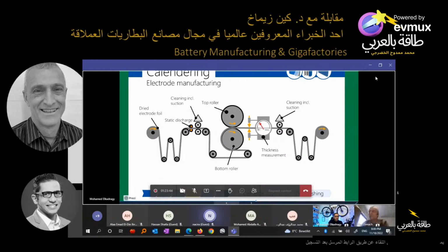Now you could say, oh, well, let's put more energy in my electrode. Let's crush it even more. Well, then your pores become too small and you can't get your lithium ions in and out. So there's a balance there. If you crush it less, lithium ions go in and out faster. It's faster charge and discharge, but you fit less total energy in your cell. If you crush it more, now you can pack more electrode in your cell, but your charge and discharge rate, how fast you can charge, how much power you can get out, goes down. So there's a trade-off, and that's all part of the cell design.